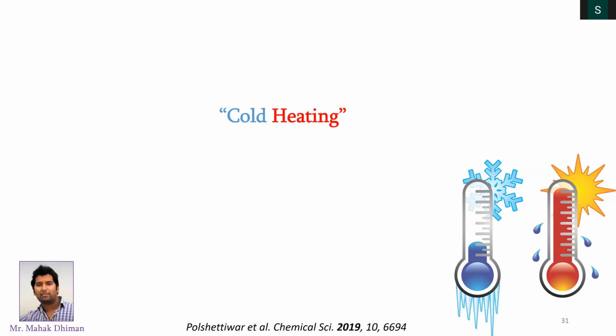What I mean to say here is, when I do catalysis, and when I'm saying that catalysis is happening at 400 degrees Celsius, you need that 400 degrees Celsius only at the active site where you have to overcome the activation energy. Ideally, I don't need to heat the entire reactor if I can manage to get 400 degrees Celsius at the active site. So your reactor can be cold or at room temperature, but your active site can be at 400 degrees Celsius. Can something like that be done?